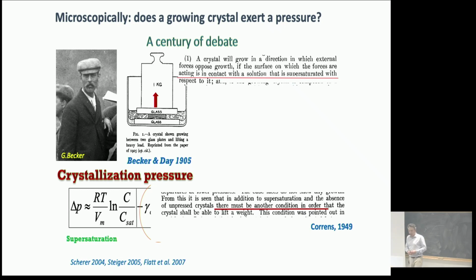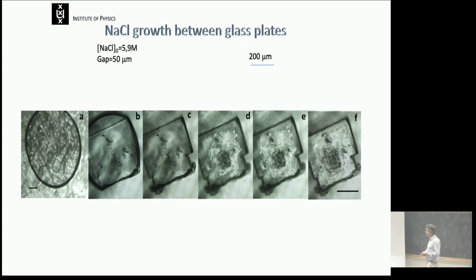Yeah, and so that was known theoretically, but experimentally, it's actually only very recently that we succeeded in providing what I think is convincing evidence. And so the experiment is practically just as simple as the crystal between two plates. We have a drop of salt water between two rheometer plates. The rheometer still measures the normal force. We let the droplet evaporate. A salt crystal starts to form.